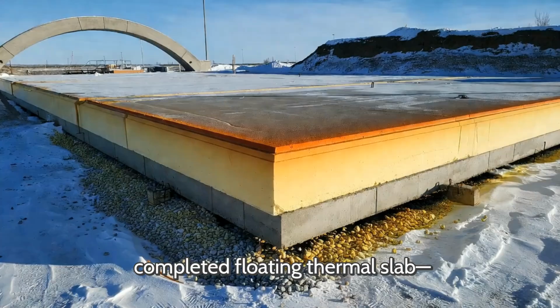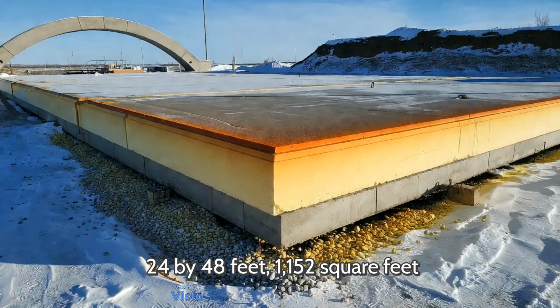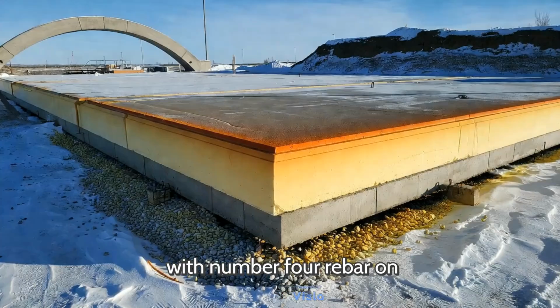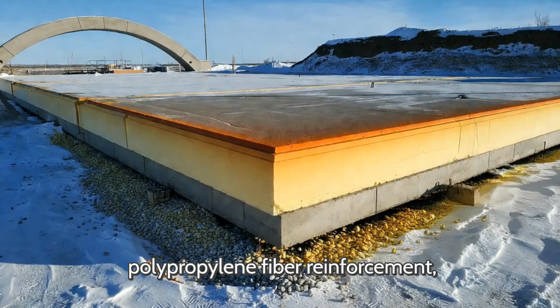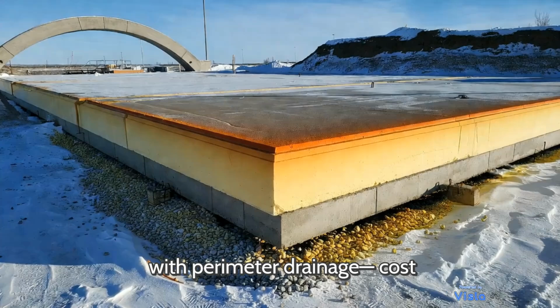The completed floating thermal slab, 24 by 48 feet, 1,152 square feet of interior floor area, 6 inches thick, 5,000 psi concrete with number 4 rebar on 12-inch centers and polypropylene fiber reinforcement, sitting on 4 inches of Type 9 XPS over compacted coarse gravel with perimeter drainage.